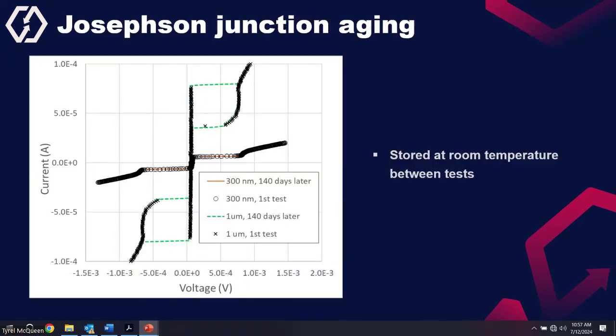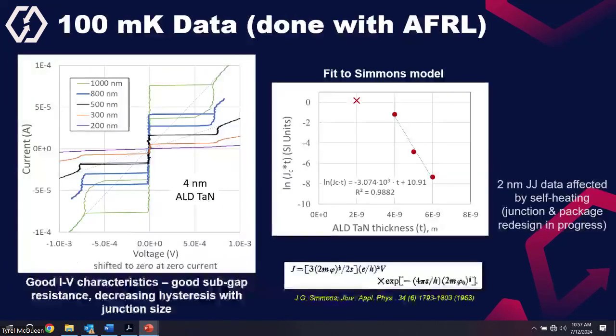Did you literally pull the whole 300 millimeter wafer, or was it cut up first? We diced it at the TAP facility in Rochester. We send the wafers there, they dice it, and we get small chiplets like 5 millimeter by 5 millimeter. And then we measured this at Air Force Research Lab, Rome, in their adiabatic demagnetization refrigerator.